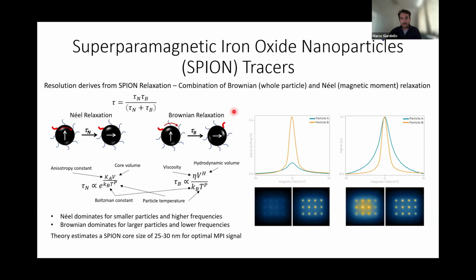So that previous slide showed the derivation of your peak, you create what you call point spread functions. These are the images at the bottom, and this is a derived point spread function that you can get either from relaxometry or from the image. And this one on the left-hand side is showing the sensitivity of two particles. Particle A clearly has a very good response, so it's much more sensitive than particle B.